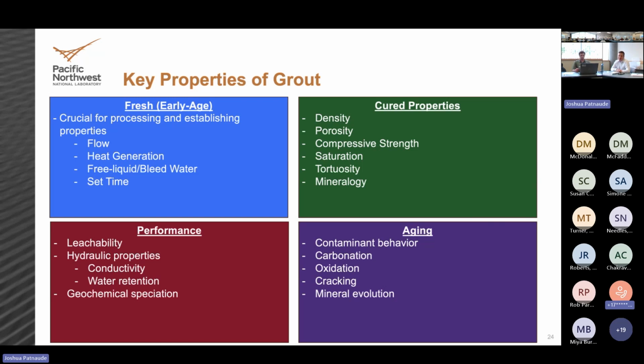You don't want it setting in the mixer, but the quicker it sets, the quicker you can move it down the assembly line and move it out towards disposal. So it's always trying to find a balance between something that we can continually process. If you have a continuous process, similar to what WTP has or what Saltstone uses, you don't want quick set times, but if you're doing more batch mixing, quicker set time is good because you can mix it up, ensure it's set, move it on.